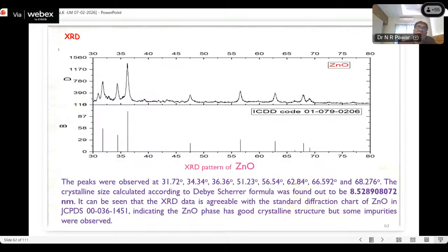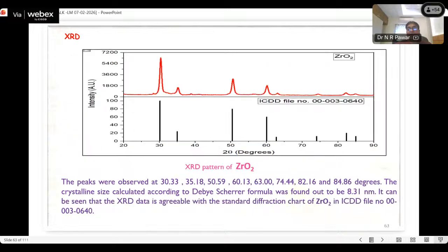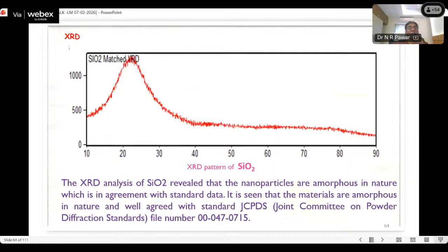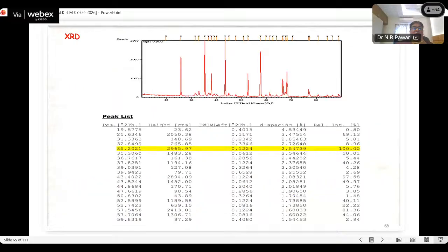This is the XRD pattern of ZnO, and this nanoparticle we use for the synthesis of the hybrid nanofluid. The peaks were observed here. The crystalline size was calculated according to that formula, and found to be this. Then it is compared with the available data. Our XRD pattern exactly matches the available pattern. This is the XRD pattern of ZrO2. Again, we observe that this pattern also matches the available data, that is ICDD file number 0030640, and this is the XRD pattern of the SiO2 that was also observed.